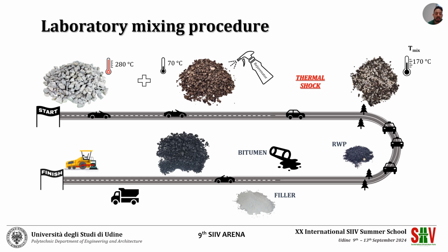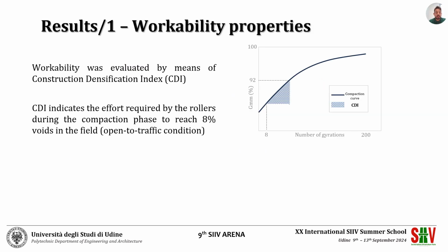Finally, the blend was further mixed to simulate the action of a paver. In this study, workability properties were assessed by using the Construction Densification Index (CDI). The CDI is calculated as the area under the compaction curve of gyratory specimens from the 8th rotation up to the one corresponding to 92% of compaction. Specifically, the lower the CDI, the better the workability of the mixture.